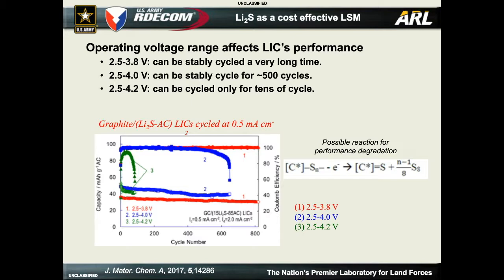Now, the one drawback of this approach is that it limits your voltage range for cycling. But for a typical LIC, you're going to cycle up to about 3.8 volts. And so at that condition, the performance is as expected.